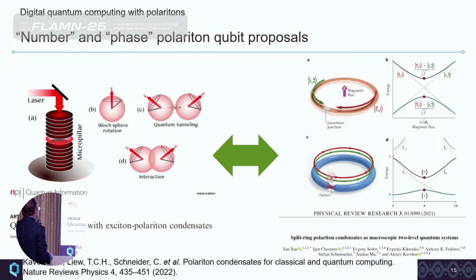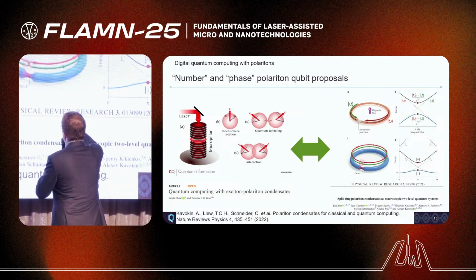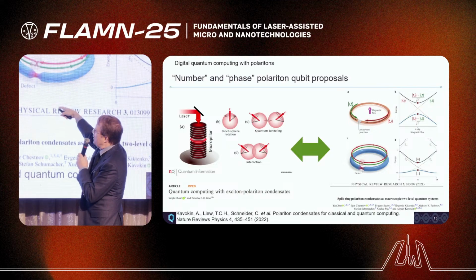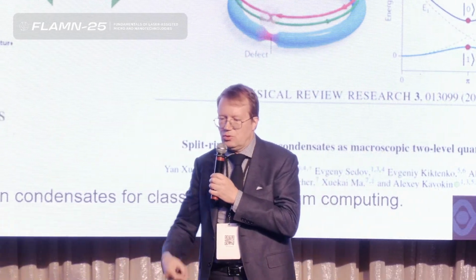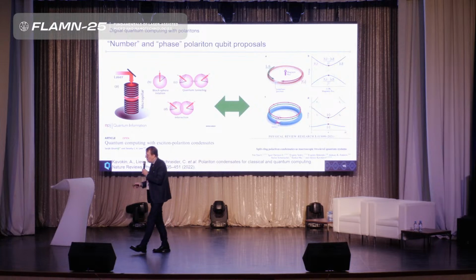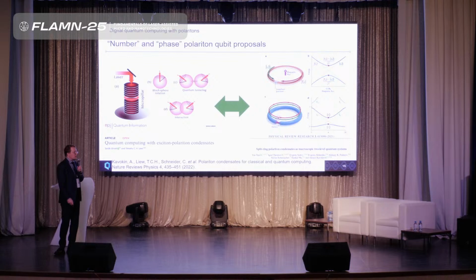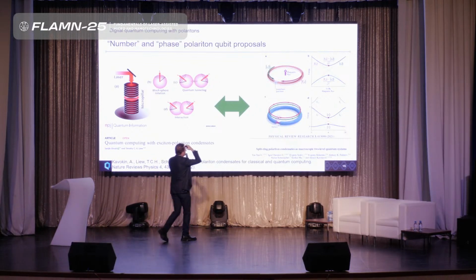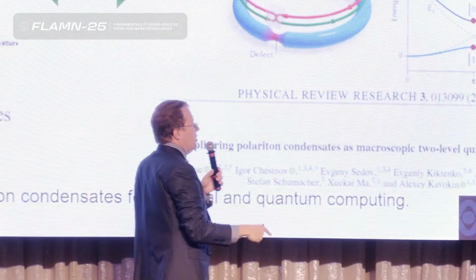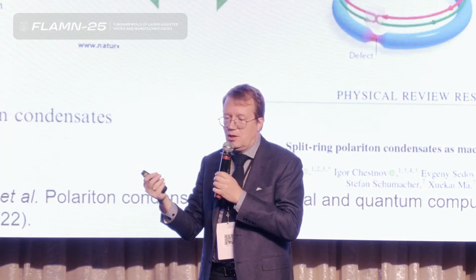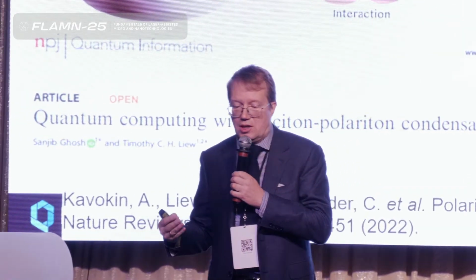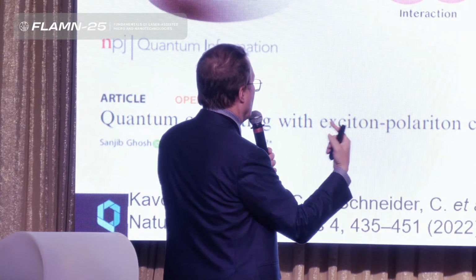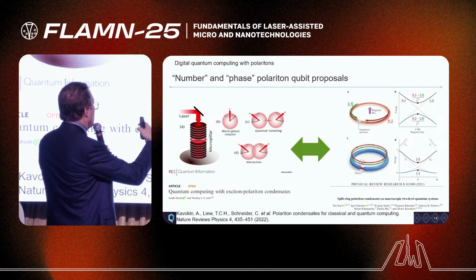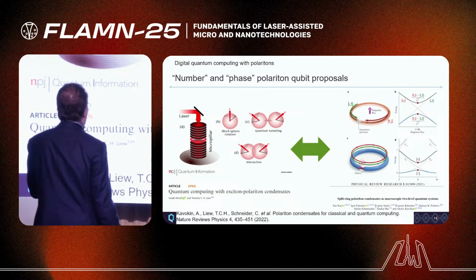But flux qubits appear to be much more robust. So this is the first theoretical proposal, which is based on the same idea of a circular trap, like in Snoke's experiments. We know that we can induce superfluid current in a circular trap. It would not decay, so it is very robust. It can exist for hours or longer as long as you keep pumping. And it is quantized because the momentum, the phase of this superfluid flow, is quantized. When you go around the circle, you may only change your phase by an integer number of 2 pi. And this gives you a discrete spectrum of quantum states. So take 2 of these states and make your qubit on them, for example, on the states corresponding to clockwise and anti-clockwise currents. And their superpositions would give you the basis, exactly like it happens in the superconducting flux qubit.